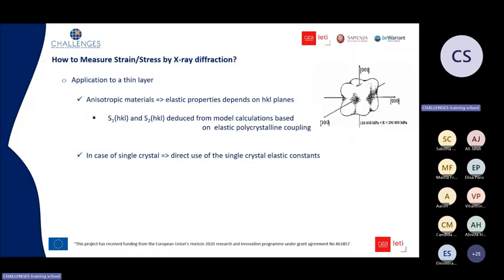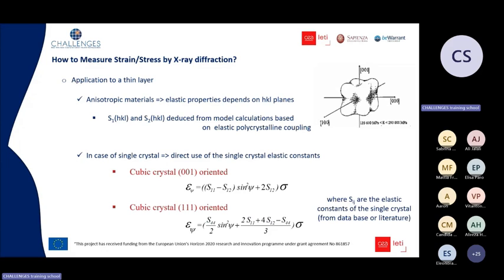There is one specific case, the case of single crystal materials, and here we can use directly the single crystal elastic constants. For instance, here for two basic cases, so a cubic crystal with the 001 orientation, the strain is related to the stress through this simple equation where S11, S12, and S12 here again are the elastic constants of the single crystal. And here you have this equation for the 111 film.